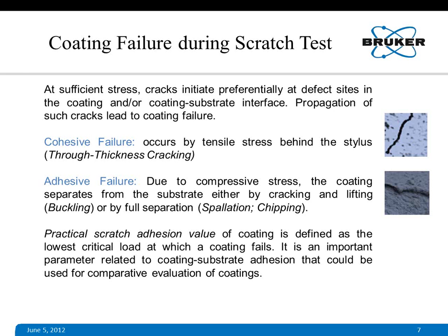Coating failure modes during scratch test. There could be two different types of coating failure. One is called cohesive failure, as shown here on the right side. In cohesive failure, the coating fails within itself. An example is through thickness coating cracks. It doesn't fail through the interface of coating and substrate. When it fails through the interface, it is called adhesive failure. Examples are buckling, spallation, chipping.